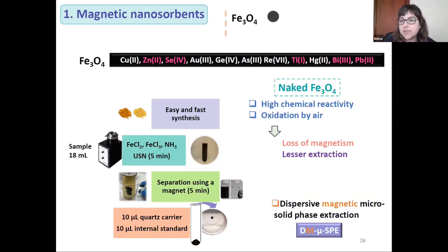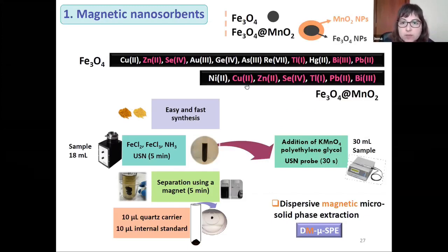However, these naked magnetite nanoparticles have a high chemical reactivity and can be oxidized by air, resulting in a loss of magnetism. Thus, it could also be interesting to improve the extraction obtained by these naked nanoparticles by using, for example, another metal oxide that has higher adsorption for metals, that is manganese dioxide. In this case, we use the analytes also shown in this lower part, and we use the magnetite nanoparticles as the core of the particles covered with a shell of manganese dioxide. The synthesis consists only of the addition of potassium permanganate and polyethylene glycol to a few microliters of magnetite in the sample solution. And here we use the ultrasonic probe only for 30 seconds since it is more powerful than the cup horn sonoreactor, and the coprecipitation of the elements is produced.